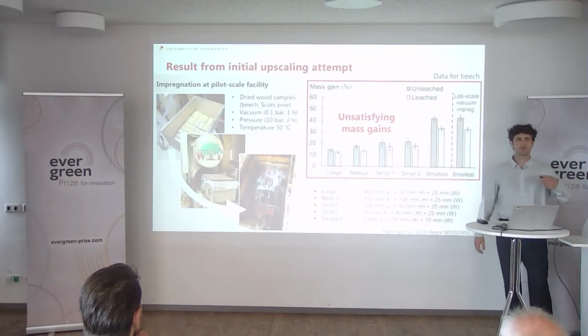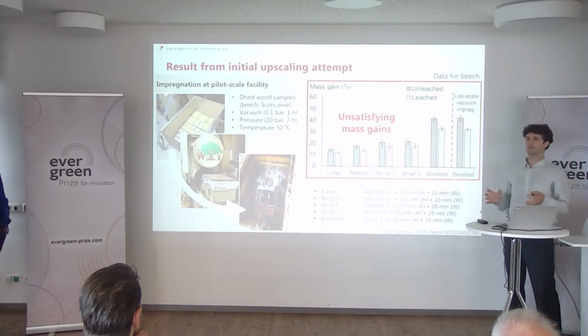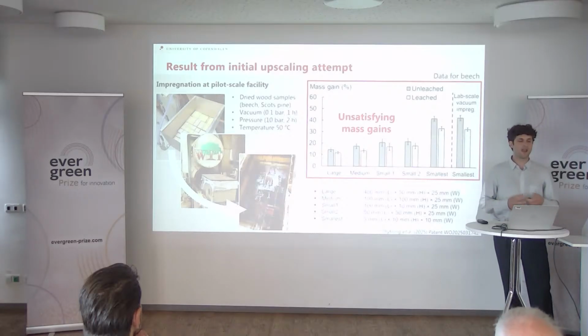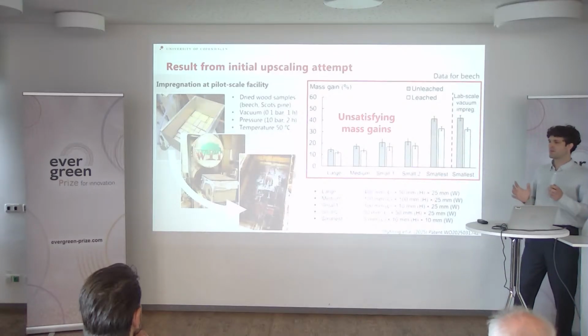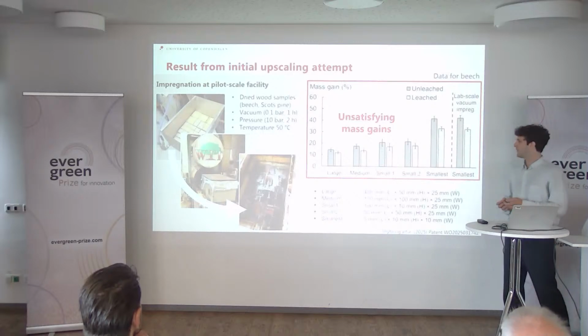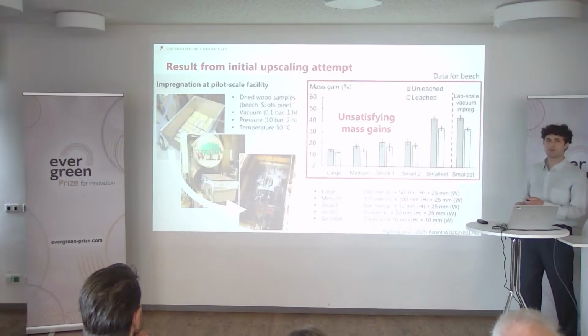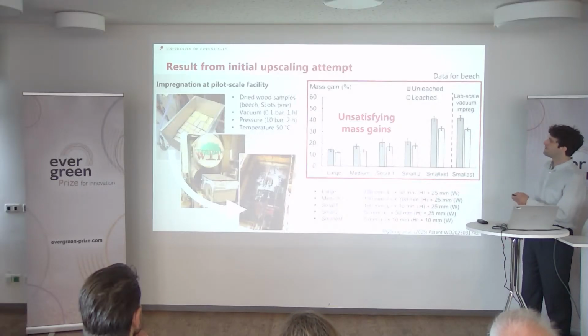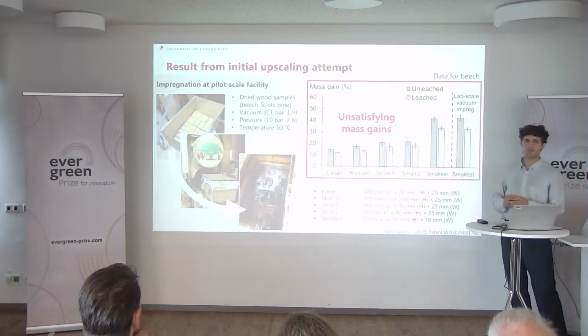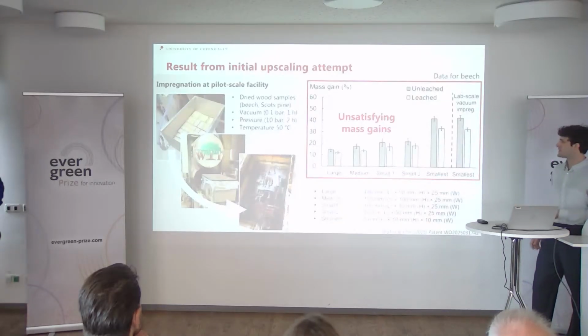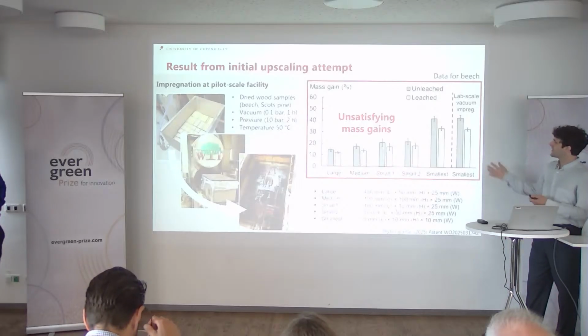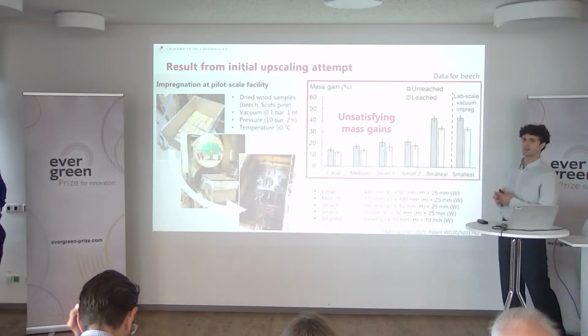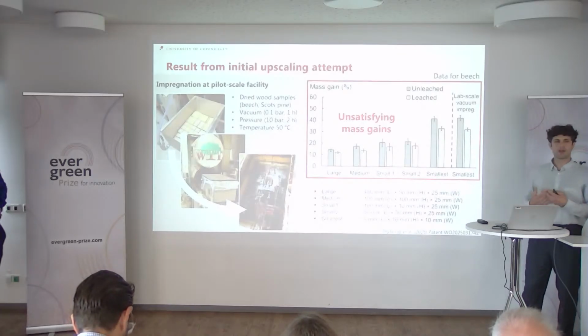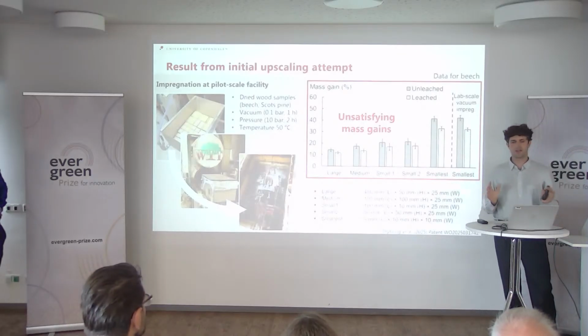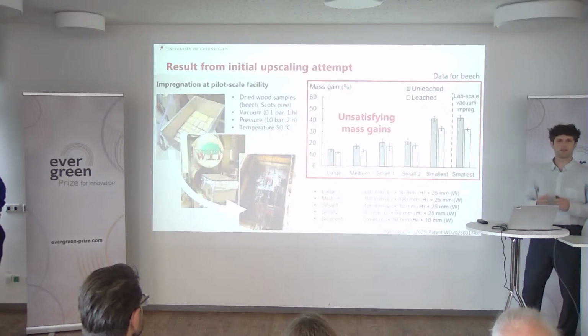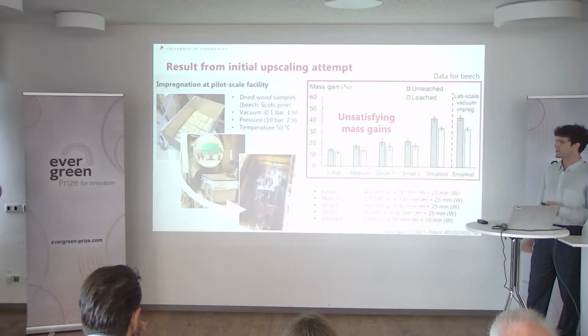And then we took two steps forward and tried to upscale this, and went to an industrial facility and asked ourselves if we could just plug and play this into an existing facility. So we brought our small samples, but also larger samples, to a pilot-scale industrial facility, with pressure and temperature at 50 degrees, so nothing fancy there. And what we saw is that though we got unsatisfying mass gain in some cases in larger samples, lower than in small scale, the key point was that we were able to use this in a facility without changing parameters, without big modifications, and with no safety hazard. So very excited about this.